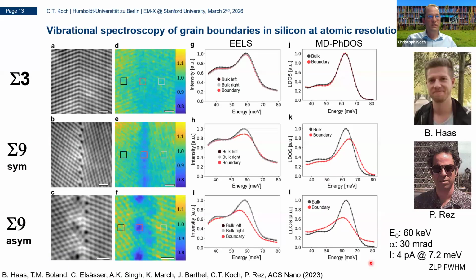Using this EELS system attached to the Nion Hermes microscope, Benedikt Haas has been able to record maps of phonon spectra across a grain boundary, or actually three different grain boundaries in a silicon sample. This is silicon 110, but there was a triple junction of three boundaries. One was a sigma 3 boundary, another was a symmetric sigma 9 boundary, and another was an asymmetric sigma 9 grain boundary. You can see here from these STEM images, they were recorded with a high current setting, so we don't have the ultimate resolution in these images. Changing that would easily resolve the dumbbells, but with these high current settings and small monochromator settings, he was able to see EELS spectra at every position. Here you can see a map which filters only the 60 milli-eV peak, so putting a filter on the spectra, showing only the 60 milli-eV peak.